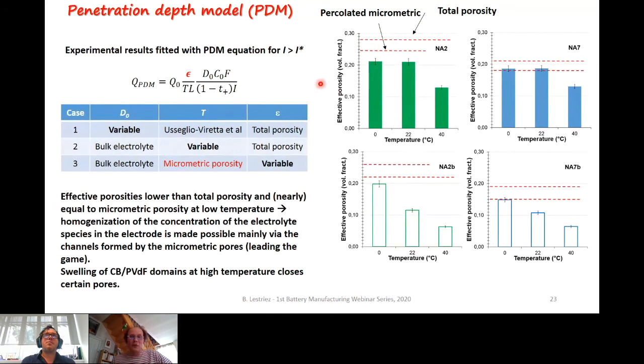In all cases, the effective porosity appears lower than the total porosity. And for some electrodes, in particular Na7, Na7b at low temperature, or Na2b at low temperature also, you see that the effective porosity seems to reduce to the percolated micrometric porosity, in fact. For other electrodes, in particular Na2b and Na7b, you have a strong decrease of the effective porosity, which is in agreement with our hypothesis, that is to say that it is the micrometric porosity that is leading the game, that is the most important to homogenize the lithium salt concentration gradient, and that the swelling of the CB-PVDF phase may result in the loss of percolation at some point in this micrometric network.